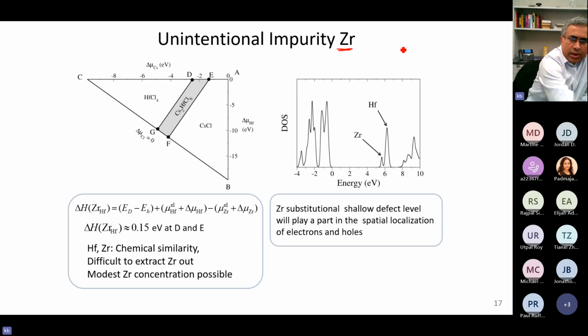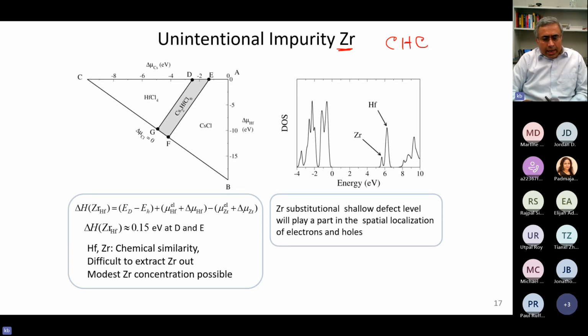Why talk about zirconium? This is zirconium in CHC, because zirconium could be an unintentional impurity. Zirconium and hafnium are like brothers. They are chemically very similar. I think their ionic radius is also very similar, and they form very similar chemical compounds. Because of all those similarities, if you grow cesium hafnium chloride, there is a very good chance that there is zirconium there, and you cannot easily take it out. Because hafnium and zirconium are so similar, you will not be able to easily purify CHC by removing zirconium. So that could be a problem, and that is indeed a potential problem.